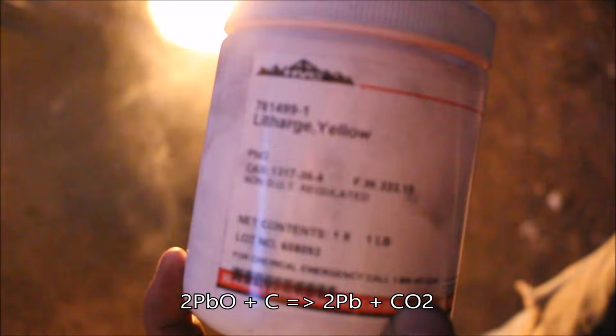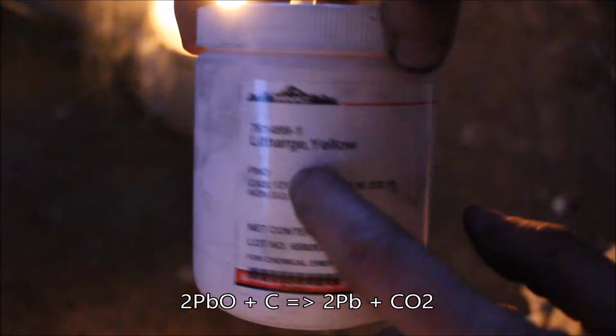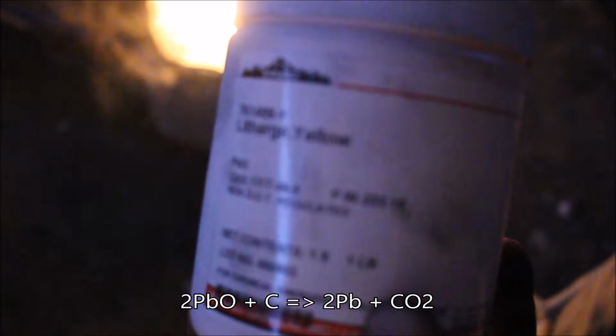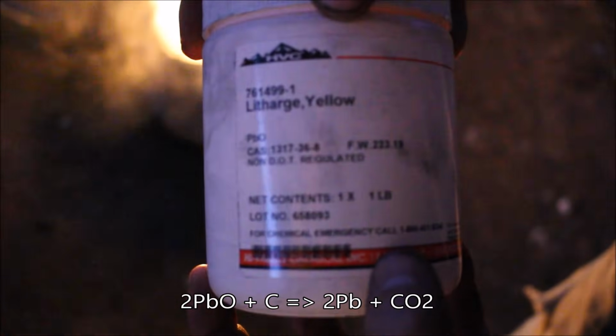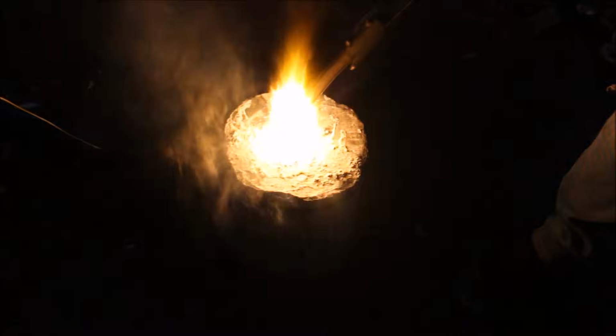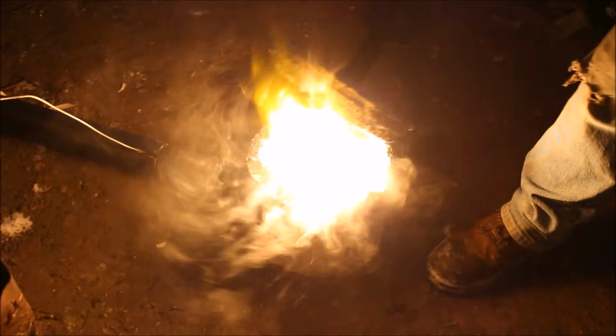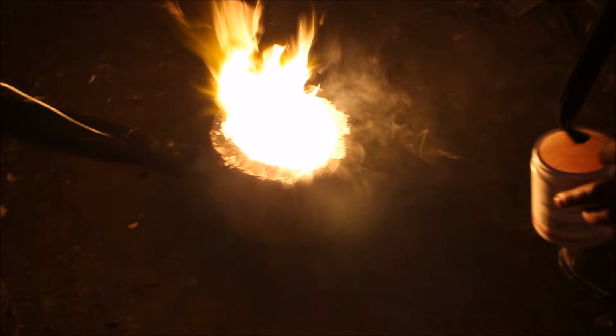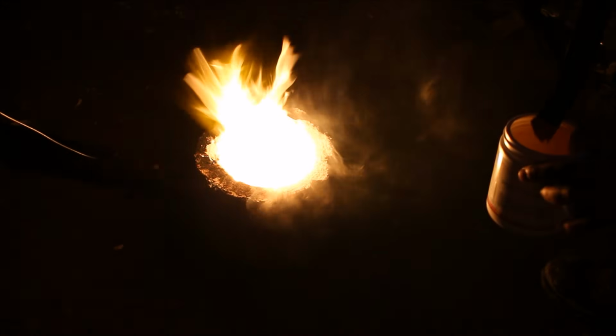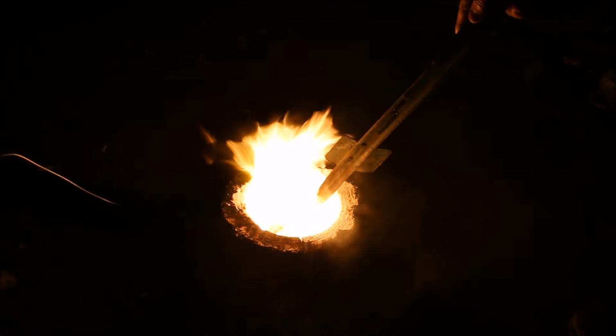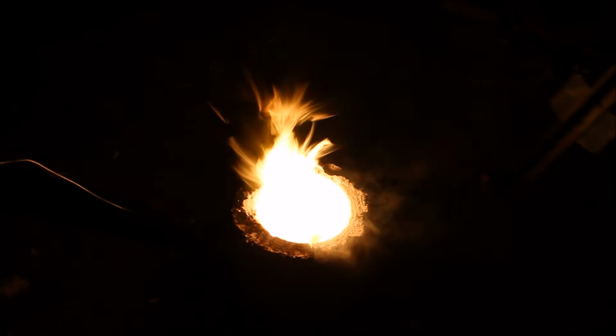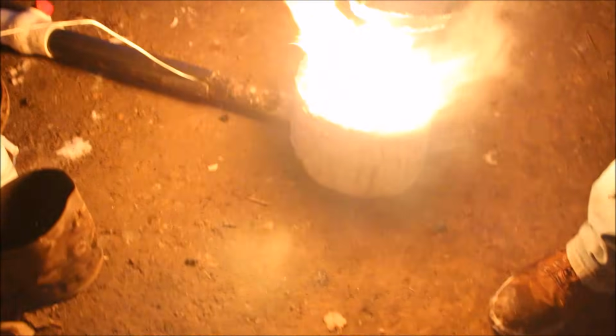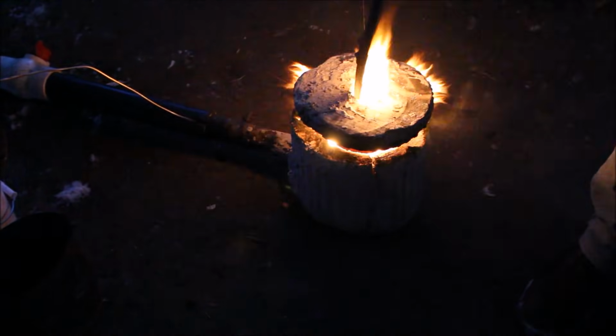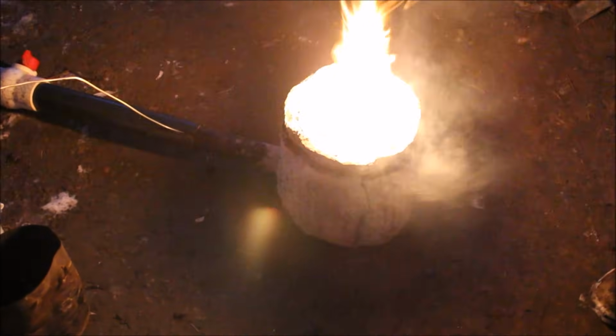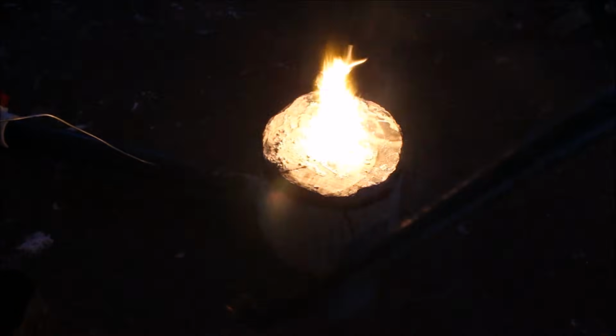So it looks like it's getting pretty hot, but not quite hot enough to melt gold. So I'm going to mix in some litharge, which is basically lead oxide, which will react with any carbon that's in there. I may have to put a little carbon, in fact. So this will turn into lead, which will collect all the gold particles and rain them down to the bottom of the crucible. That'll help collect the gold into a solid piece.